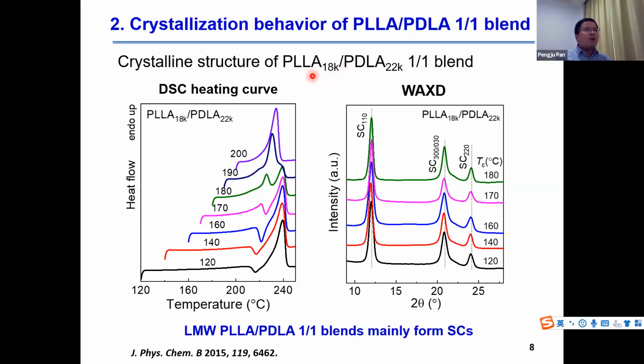For the low molecular weight system, the molecular weight of PLA and PDLA is about 20,000. With a low molecular weight, PLA and PDLA are also thermocrystallized in the temperature range from 120 to 200 degrees C. We only observe the melting peak of stereocomplex crystal in the DSC and the diffraction peak of stereocomplex in the WAXD. This means the low molecular weight blend lacks the homocrystal crystallization.